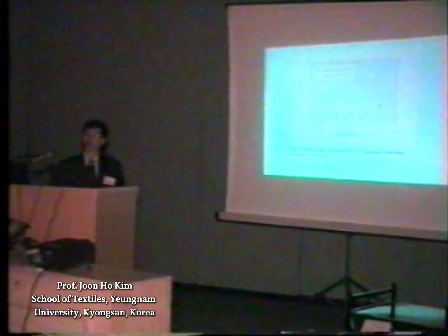Figure 9 shows the plot of rate constant of PTT hydrolysis with heat treatment temperature. The white circle denotes the methanolic result and the black one denotes the aqueous medium. The methanolic hydrolysis was much faster than the aqueous medium, and the heat treatment effect was predominant for methanolic hydrolysis.